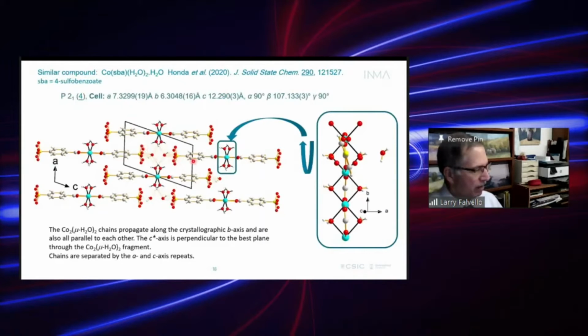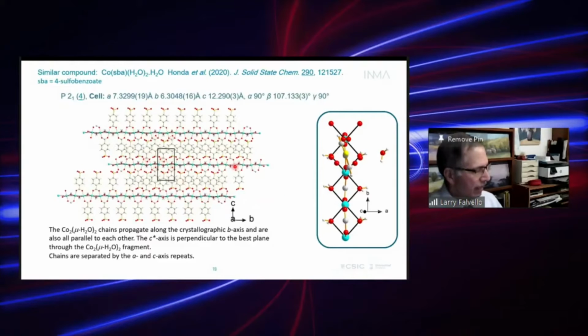And so the ribbon is in the crystal structure, same with ours. And here's the point I wanted to get to. All the ribbons in the structure are parallel to each other. When we look at a crystal structure, a crystal structure is solved for only the asymmetric unit, and that appears explicitly, and then the rest is generated by the symmetry elements of the space group. Sometimes we lose sight of the fact that the different symmetry-related molecules are not necessarily parallel to each other. In this case, they are, and well separated.